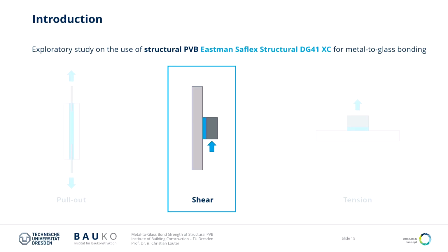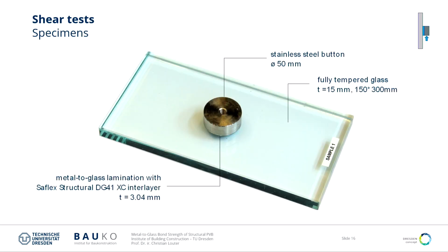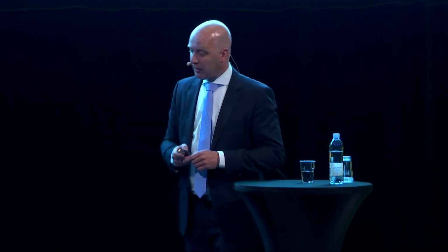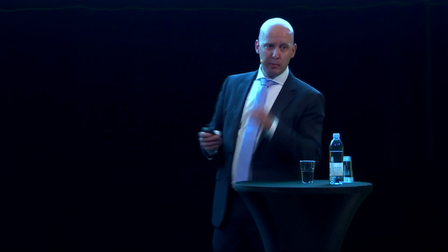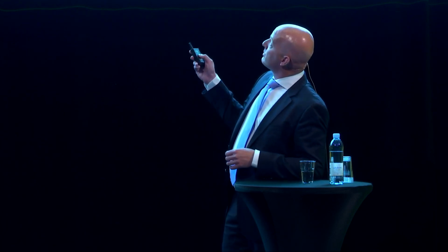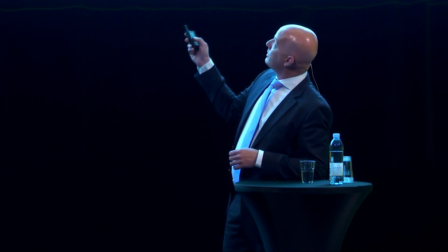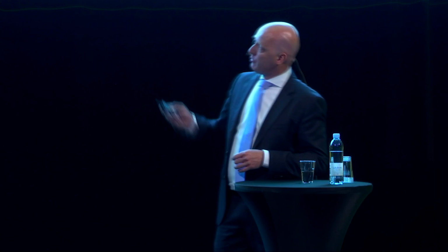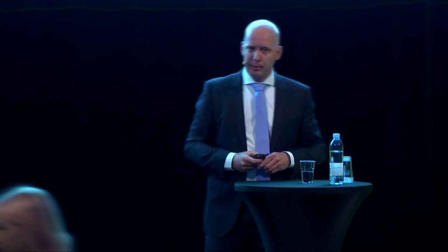The next test that we did was a shear test. In this case, we laminated something on the outside of the glass. You can see the specimen here. So it's a fully tempered piece of glass, 15 millimeters thick. And then we laminated this stainless steel button on top of the glass using the structural PVB at this point. And again, we have used 4 layers of interlayer to reach 3.04 millimeters of thickness.